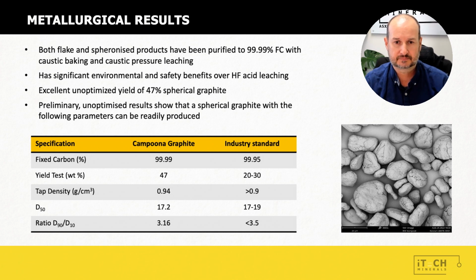So the final criteria is the ratio of D90 to D10, and that is the variability of the size of those particles. The more evenly sized or less variable they are, the more consistent the performance of your battery. And you can see we came in well below 3.5, which is the industry standard, at 3.16. So overall, we nailed all of those industry standards, and we have a very high quality spherical graphite for use in battery anode material.